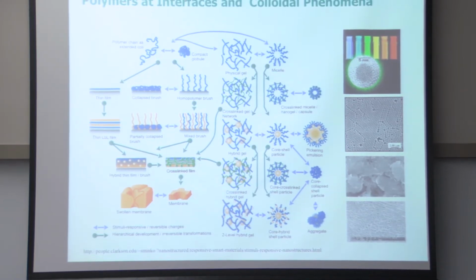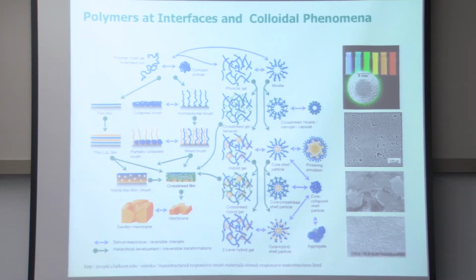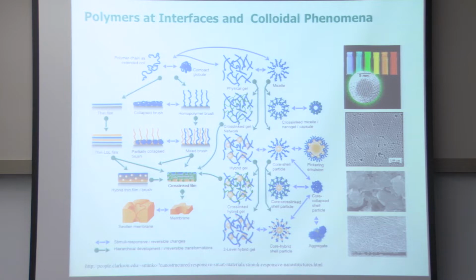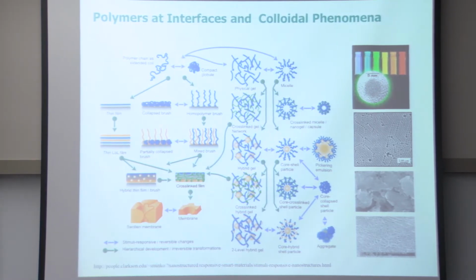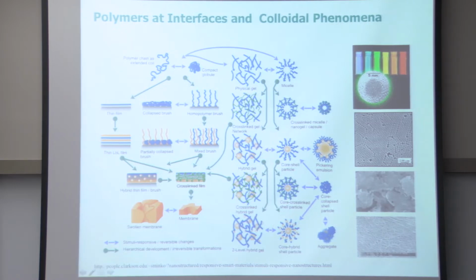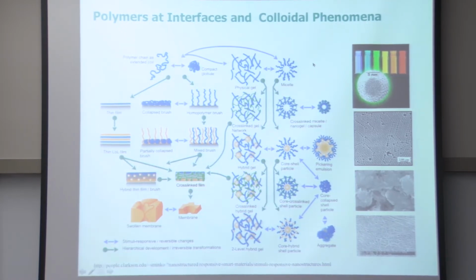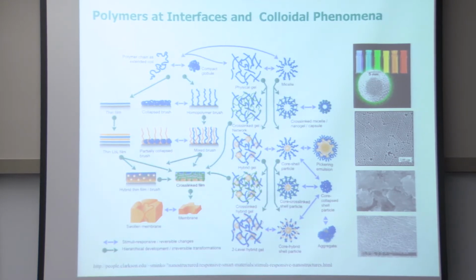In other words, polymers play an important role in the balance between the hydrophilic, lipophilic interaction on the interfacial phenomena. So you can have polymers that can be miscible or immiscible with various solvents, or you can have very stable Pickering emulsions that can stabilize emulsions in oil and water. So truly, we can say that a polymer is a nanomaterial. It is capable of interaction and manipulation at the nano level, much like we can use carbon nanotubes, nanocrystals, gold nanoparticles, graphene, etc. I can see, or you should see, polymers in the light of this type of nanomaterials.